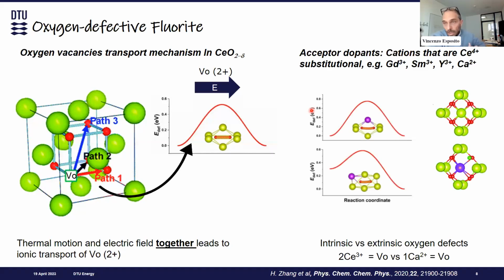And of course, this transport effect depends on many things. One of the important parameters that we are considering is the local distortion, which is due, for example, to the dopants that we are using in the material. The dopants here are usually elements that have a lower valency, so they can induce the formation of vacancies, but at the same time, they induce some electrostatic distortion of the lattice. And this can change the ionic conductivity.